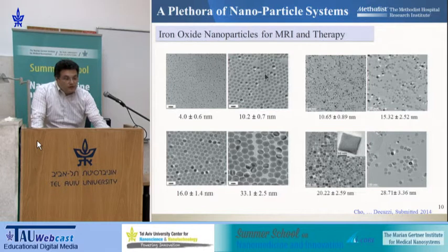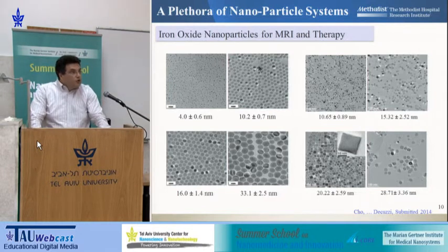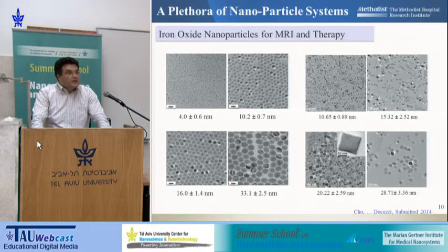We're also working on iron oxide nanoparticles, iron oxide nanocubes. Again, the spherical shape, yes, it's fine. It's probably the easiest that you can get because self-assembly and energy minimization will take you to a spherical shape. If you want to deviate from spherical shape, of course, you have to somehow use different approaches. But there are a lot of features that you can introduce in your system if you start playing with non-spherical shape that a classical conventional spherical nanoparticle will not provide.